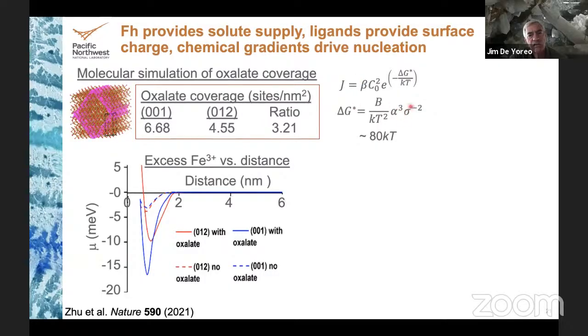Out in the bulk solution, this barrier is 80 kT. So nucleation is a rare event. But if we drop the interfacial free energy by just 5%, this nucleation rate goes up by 3 times 10 to the 8th times. It's incredibly sensitive.